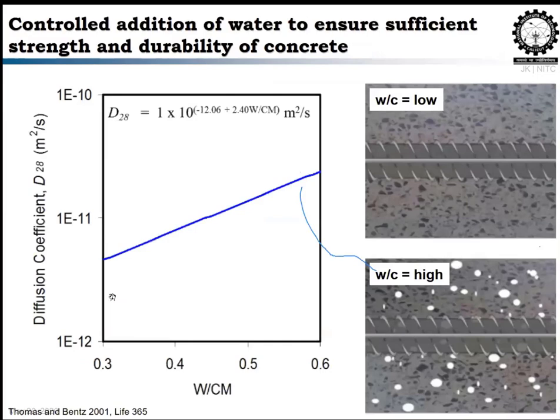So here we are looking at the diffusion coefficient for concrete with different water cement ratios. Just by making a proper proportioning based on the water cement ratio, you can achieve a very good reduction in your diffusion coefficient. The diffusion coefficient is nothing but the rate at which the aggressive environment like chlorides moves from the cover to the steel surface. Simply, the rate of movement of aggressive ions. So you can see from 0.3 to 0.6, comparing 0.3, 0.4, 0.5, it changes by one order. So it is always recommended to go for a lower water cement ratio to have a reduced diffusion coefficient. The main parameter is to have a very low water cement ratio.